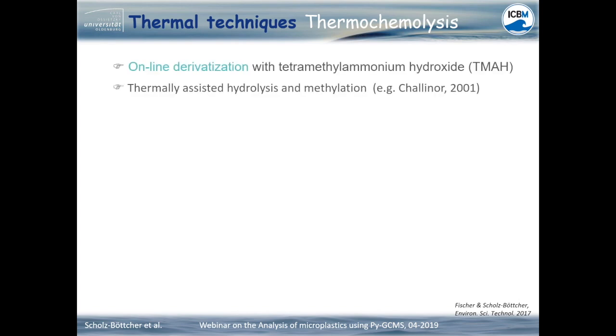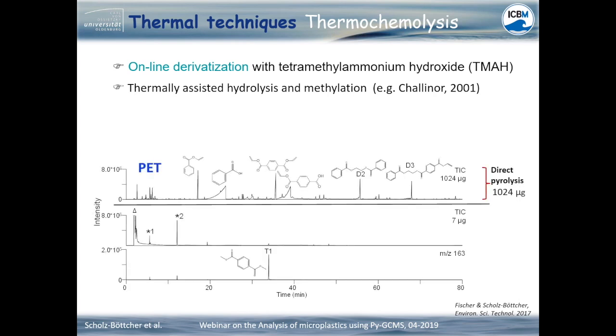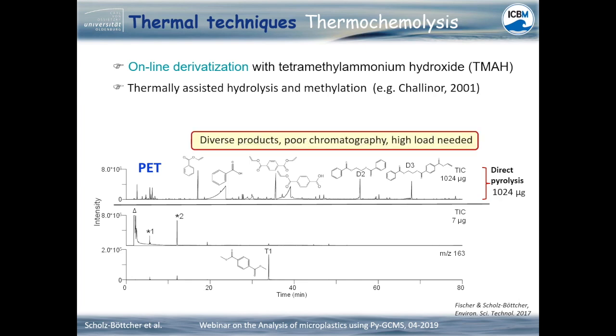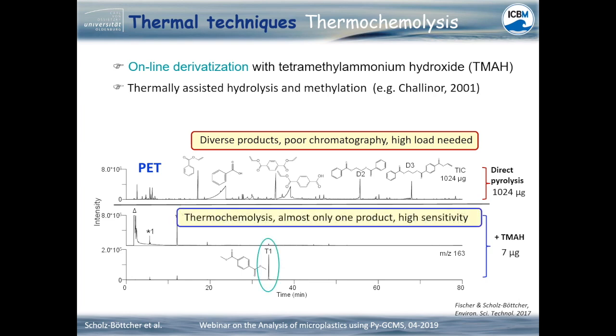Thermal techniques enable the use of online derivatization, for example thermochemolysis using tetramethylammonium hydroxide as a reagent. Polyethylene terephthalate shows a complex pyrogram with several indicative signals, but with a very poor sensitivity and chromatography after direct pyrolysis. After the addition of tetramethylammonium hydroxide for thermochemolysis, the resulting chromatogram shows almost one indicative signal only, resulting in high sensitivity concerning PET detection.